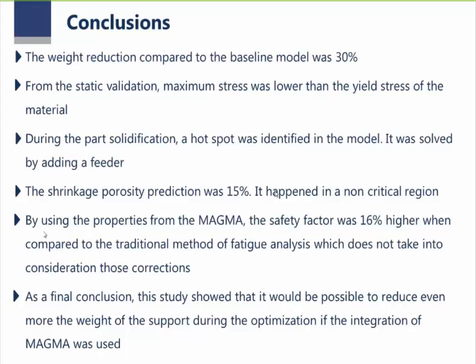So by using the MAGMA properties, the safety factor was 16% higher when compared to the traditional method, which does not take into consideration those corrections.